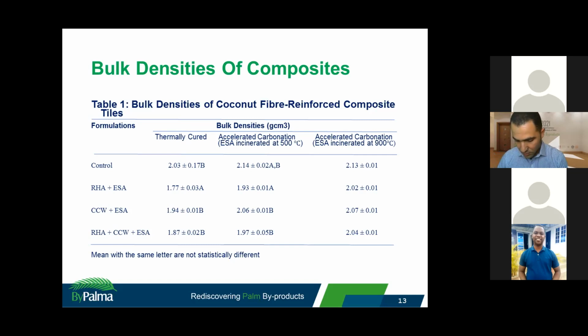And from the experiment on the sample, we find out that the eggshell incinerated at 900 degrees Celsius has a better performance. Although the bulk density increases, at 500 the bulk density was lower. But from all the formulations, the composite containing rice husk ash and eggshell ash has the lowest bulk density. It shows that the introduction of our admixtures, different raw materials, still gives us a composite that has lower density than the control, which shows that in our production of roofing tiles, we can use this admixture because it still gives us a better performance than the control.